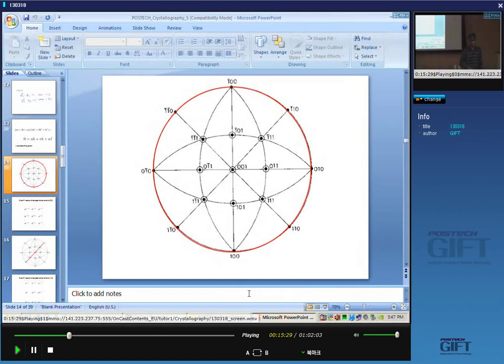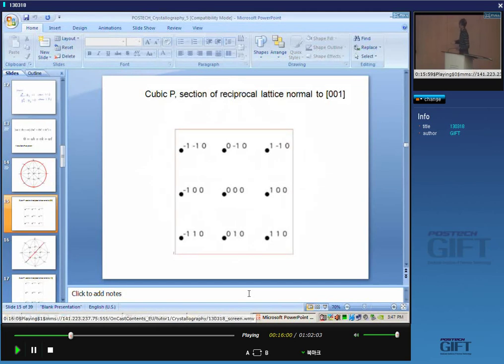Well, we follow the rule that if I can identify two vectors in that reciprocal lattice section, then all the others are straightforward. Yeah? So let me pick two convenient vectors. If I plot 1, 0, 0, and then 0, 1, 0, then all the others should follow just by linear combinations. So only the poles lying on that red circle will appear in my reciprocal lattice section. So here it is. This is a cubic P, and it's a section of the reciprocal lattice normal to 0, 0, 1. So I've got 1, 0, 0, and I've got 0, 1, 0.